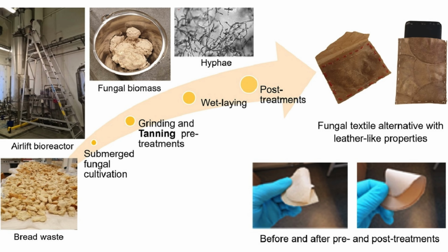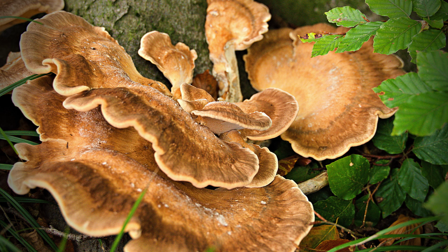The characteristics of the final leather substitutes derived from fungi depend on several factors, including the type of fungal strain used, the type of growth substrates and other growth conditions, the mode of fermentation, as well as the subsequent downstream processing. Among the fungi, white rot fungi have the most desirable properties required of the starting materials for fungal-based leather substitutes. Subsequently, the fungal inoculum can be cultivated under submerged, solid-state or liquid-state conditions for efficient product recovery.